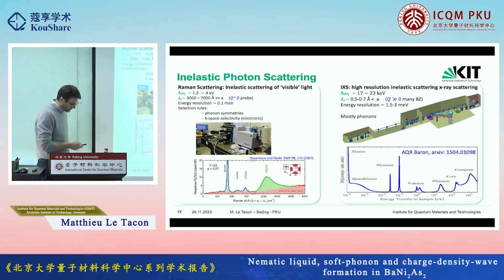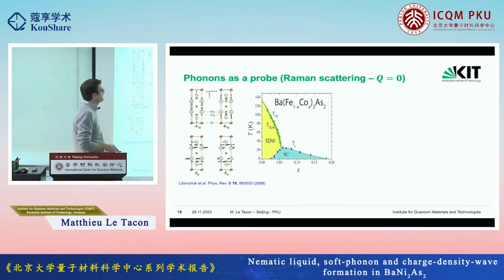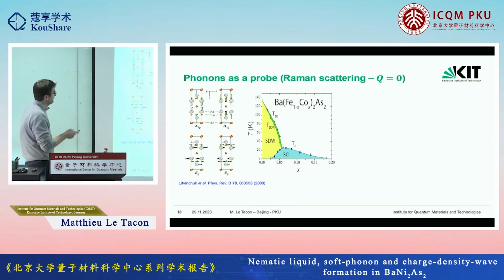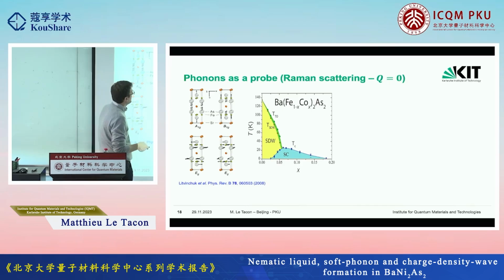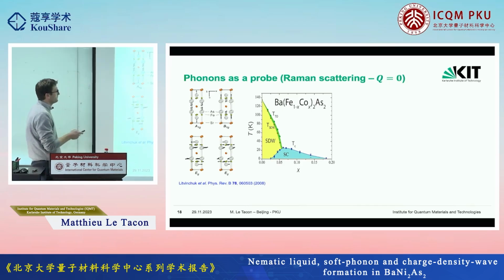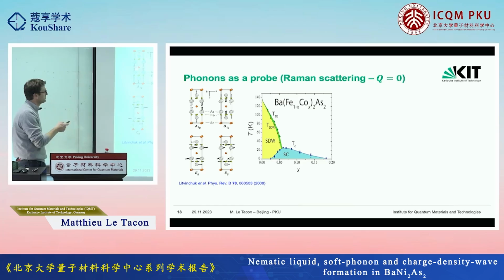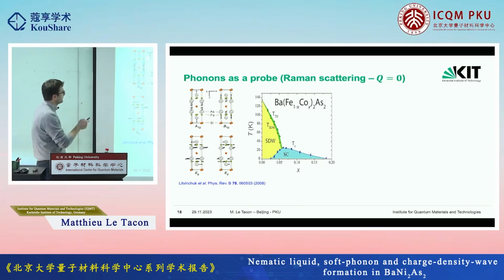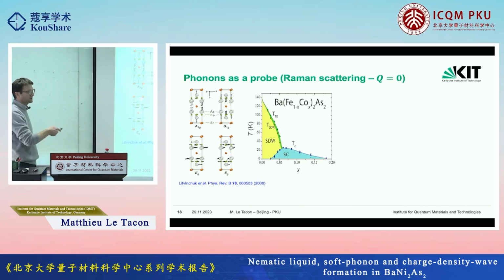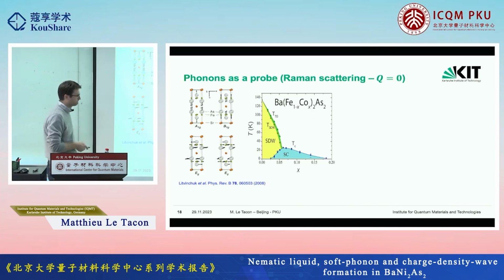So, going back to the history of this distortion here, the tetragonal distortion, I just want to show the example of the iron-based superconductor. So this system again has a tetragonal symmetry, and from the group symmetry you can look at which are the allowed phonons in the system, and you have 4 Raman active phonons, A1G, B1G, which are C-axis polarized vibrations, and you get the EG mode, which corresponds to the in-plane vibration of the iron and arsenic.